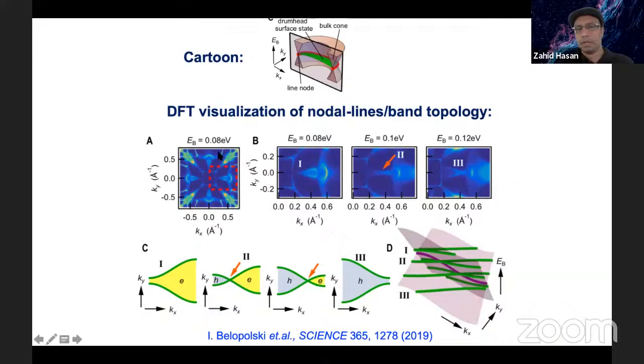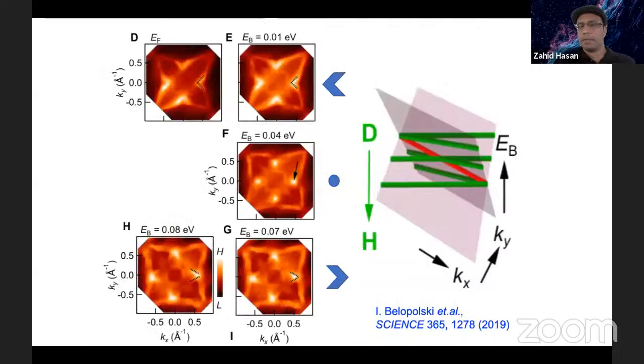So then we used ARPES to visualize this state. This material has a complicated multi-band structure. For example, in some part of the momentum space, you have this Weyl crossing, but at an energy higher than that, the band shifts like that, and here this is reversing. So this is in the theoretical prediction from our paper of how to locate the crossing and its nearby states.